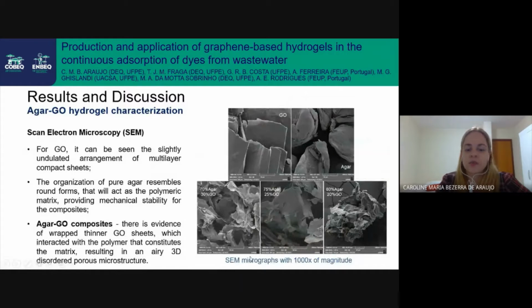We've done the scanning electron microscopy of the samples. For graphene oxide, it can be seen that it presented a slightly disordered arrangement of multi-layer compact sheets. And for the 3 samples of the hydrogel produced, we can see that overall, in all agar gel composites, there is evidence of a thin graphene sheet which interacted with the polymer that constitutes the matrix, which is agar, resulting in an airy 3D disordered porous microstructure. In this case, we lyophilized the samples in order to proceed with the analysis.